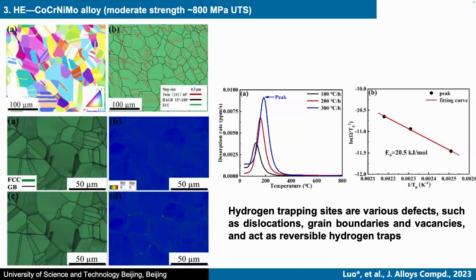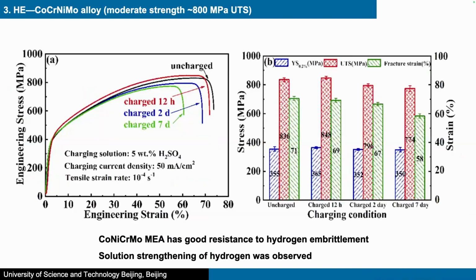It's also a moderate strength alloy. We did a similar study, such as EBSD to observe the microstructure, and TDS to measure the hydrogen trapping sites. And also we did the tensile test and found this alloy also has good resistance to hydrogen embrittlement. And also some solution strengthening is observed by hydrogen.